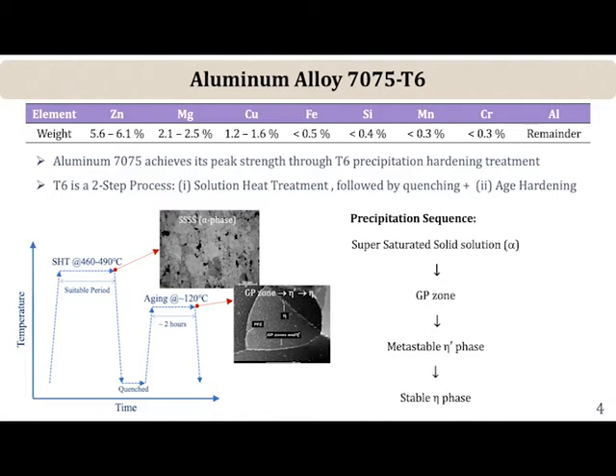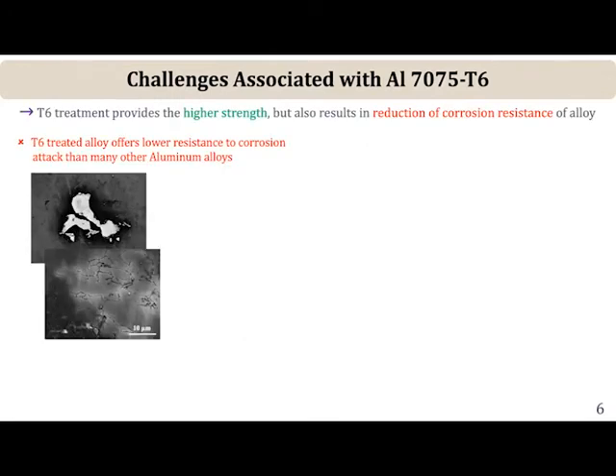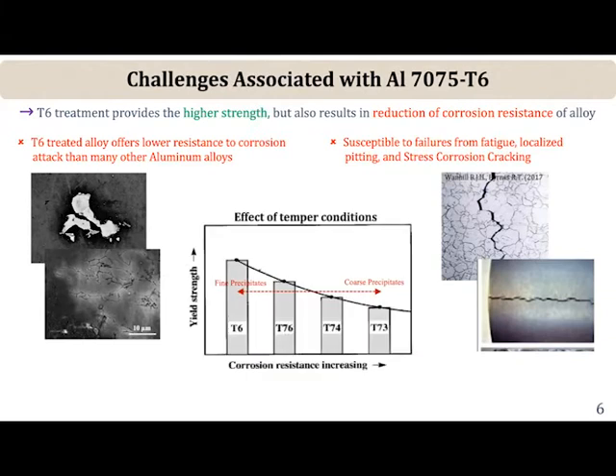And then once the pit forms, it's a local area where fatigue cracks can initiate. So this SEM micrograph here shows a typical microstructure. But as I mentioned, one of the main challenges is that the T6 treatment, although it provides a higher strength because it's a peak age condition, also reduces the corrosion resistance appreciably, right? So compared with many other aluminum alloys. In fact, corrosion and stress corrosion cracking and exfoliation and so on are problems in aluminum alloys.